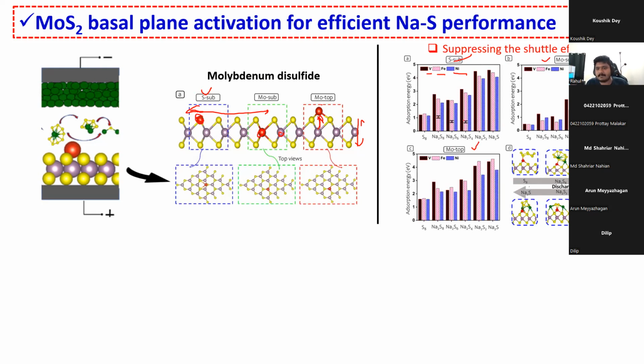We calculated the binding energy of the polysulfides with this substrate, and we found that the binding energy of the substrate with the polysulfide is higher than the binding energy of the polysulfide with the electrolyte. The binding energy of these substrates with the polysulfide is very high when compared to the electrolyte. Even for the Mo top site, we found that it's very high. But if we go to the Mo substitution site, the binding energy of the polysulfide with the electrolyte is higher when compared to that of the